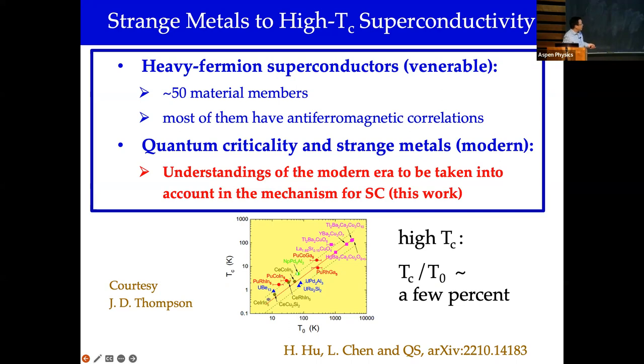This spans three to four decades on both the effective Fermi energy scale and the superconducting transition temperature. Now, if you go back to the conventional Bardeen-Cooper-Schrieffer type superconductor, Tc is usually on the order of 10 to the minus 4, or at most 10 to the minus 3, of the Fermi temperature. This slope here turns out to be a few percent, so several orders of magnitude. In that sense, maybe there's some interconnection in the microscopic physics. So learning about the mechanism of superconductivity in this class of materials, sitting at the lower left corner, could have some general implication, so we hope.